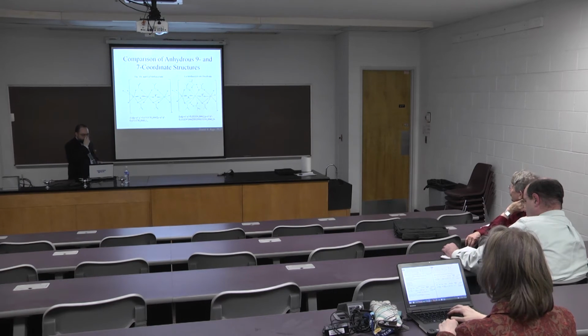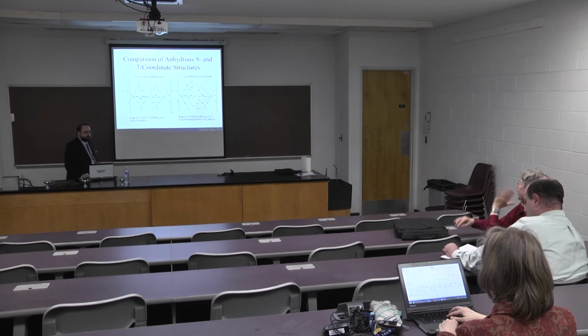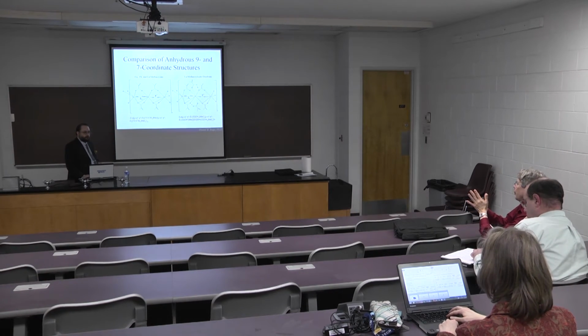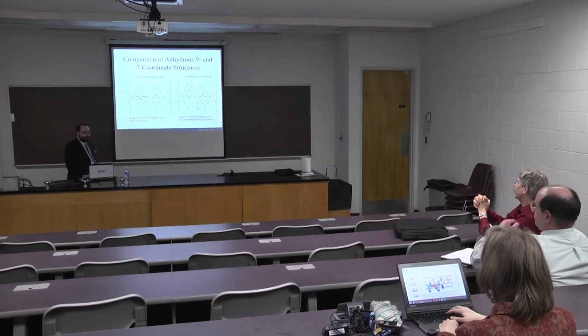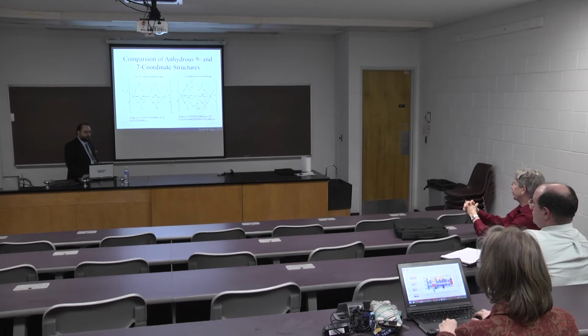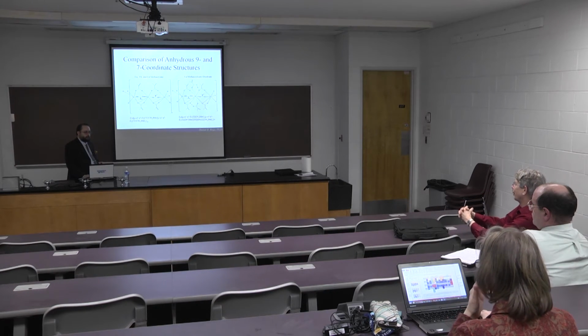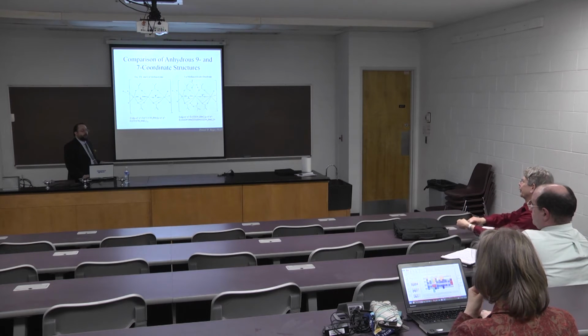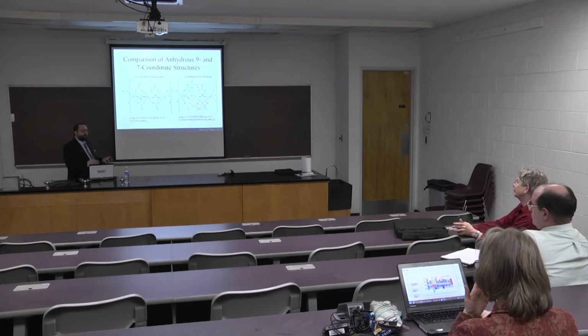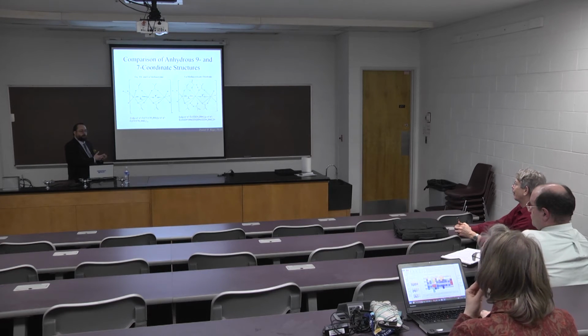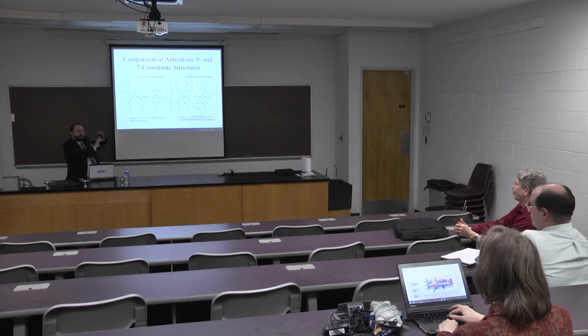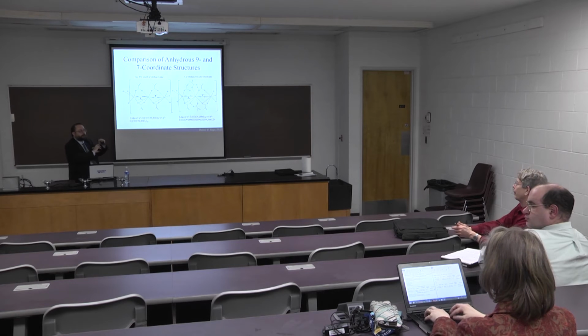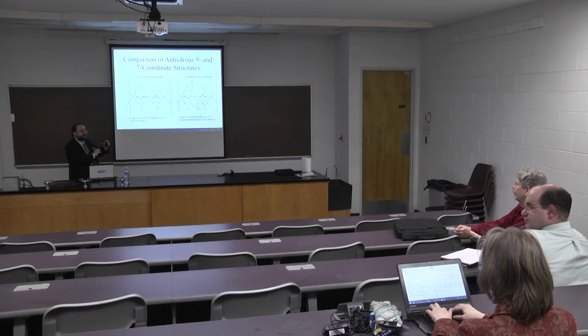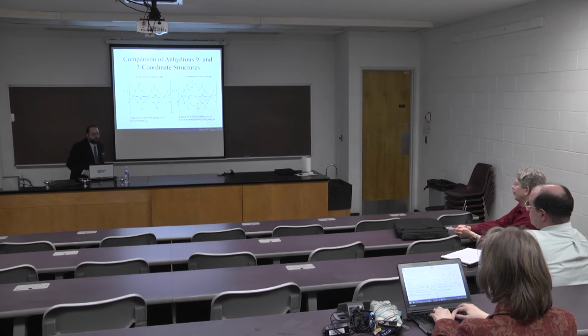This isn't a subject I know a huge amount about, but my understanding is that twinning will often show up as falsely high symmetry and poor refinement of the structure. We kind of thought that was happening because we weren't really getting good R numbers out of it. But the more we worked on it, it turned out that we were seeing both electron densities. It's not just spread all over the place, we're actually seeing it in two separate locations in the same crystal.